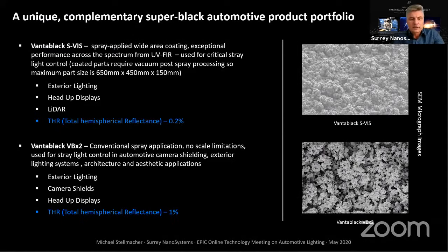Vantablack is actually not a standard black paint. As you can see in the pictures, the material has a very unique structure, very rough and you can say coral-like, which allows the coating to absorb light at almost every incidence angle.